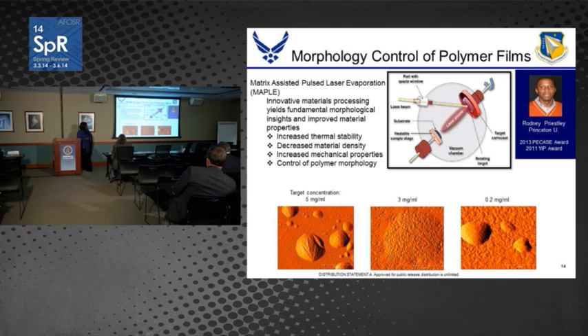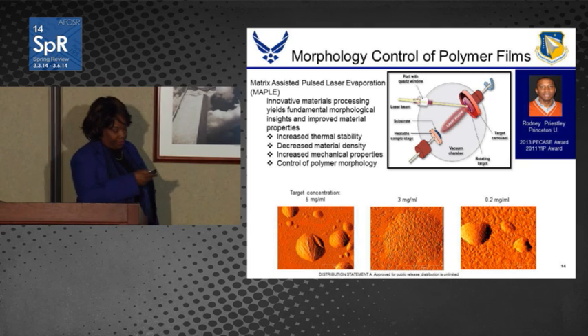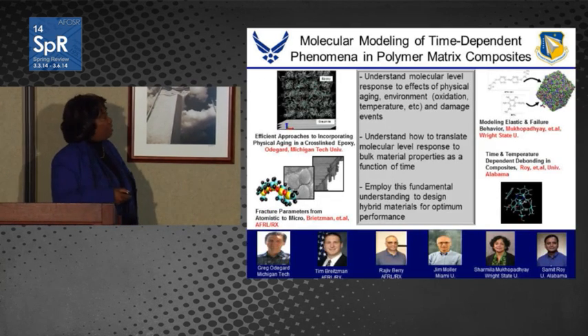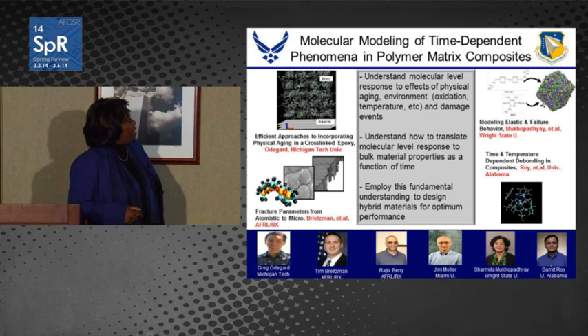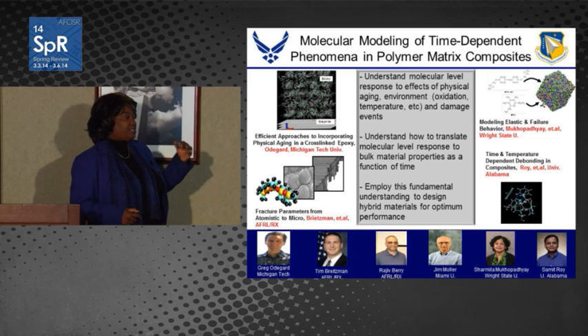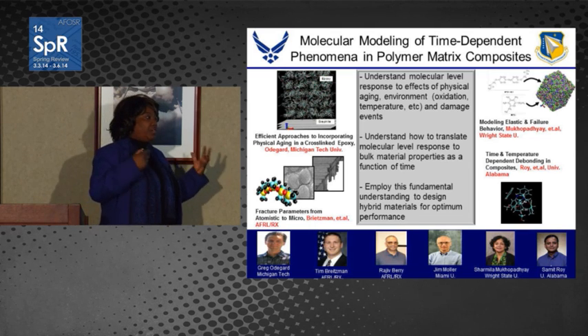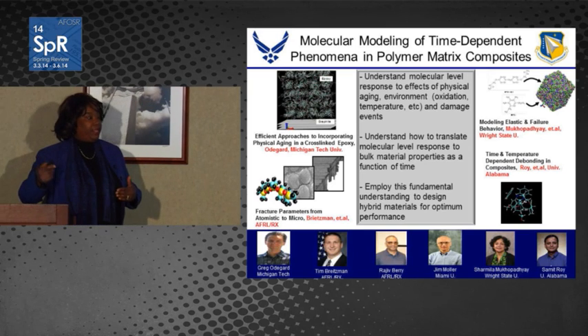And so he's been able to show that by using this technique in a very controlled way, you can make materials with significantly improved thermal stability, decreased density, increased mechanical properties and the like. And so it's a real basic research problem where we're trying to understand, in this case, processing, structure, morphology, property type relationships. Okay, last in thrust one, I mentioned we're doing work on modeling to understand how at the molecular level, like at the atomic level, these things evolve and degrade over time, to understand ultimately how that affects the structure and the degradation of the structure.